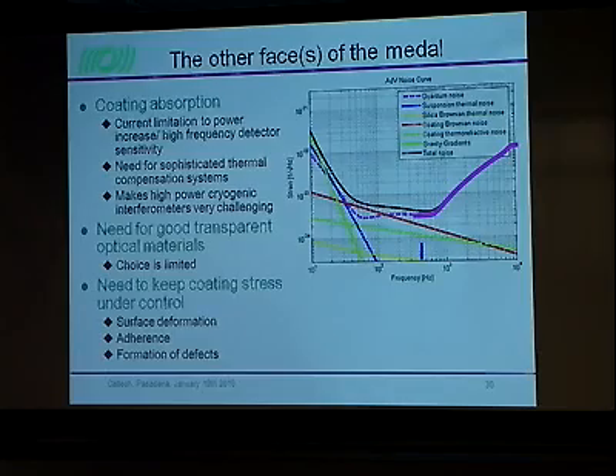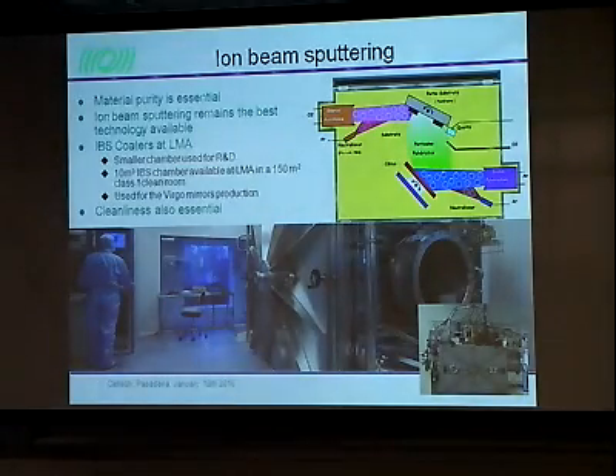The best technology we know about today in order to produce low loss coating is ion beam sputtering, at least on large surfaces as the one we want to have. We have two of these kinds of machine at LMA, where basically you use an ion beam to sputter the material from a target, which then condenses on the mirror where you want to deposit this coating.